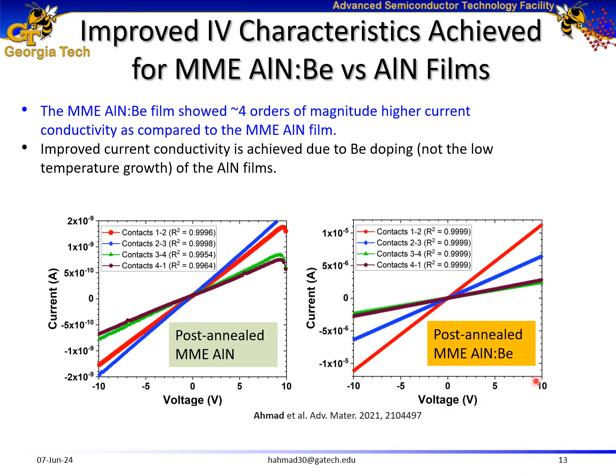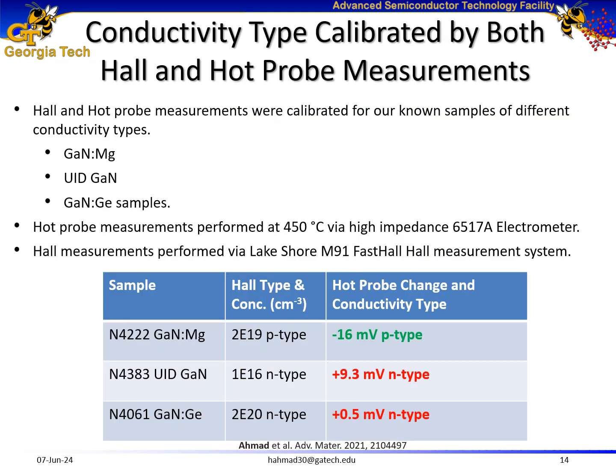Furthermore, from comparison of a beryllium-doped aluminum nitride versus annealed undoped aluminum nitride film, we see an improvement in approximately 4 orders of magnitude. So it's actually the beryllium doping which improves the conductivity of these samples. Later, I wanted to validate the conductivity type of these samples with both Hall measurements and also hot probe measurements. But first, I calibrated Hall and hot probe measurements for our standard P-type, UID, and N-type gallium nitride samples.